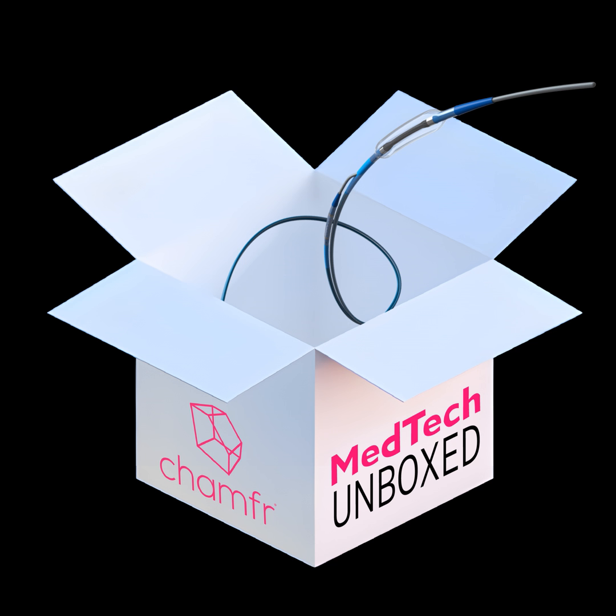Because it's dependent on test data and those tests are very standardized, many of those test standards are based on bigger parts than what we're working with in micromolding. So a lot of times we have to take that with a grain of salt. A lot of times we have to take it with a whole salt shaker and go, we really need to do our own empirical testing and get a body of data behind it, which we have over the years. And so we have a pretty reliable understanding, based on real life data, with parts just like these micro parts, these small wall sections, sub 10 thousandths wall thicknesses, long thickness to length ratios, which are particularly challenging for those pressure drop reasons we talked about. We put a lot of stock into the empirical data we get. All of that can then be fed back into the simulation databases so that you can leverage that in predictive analyses.